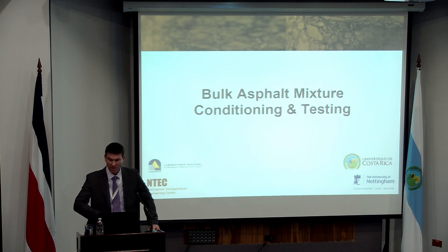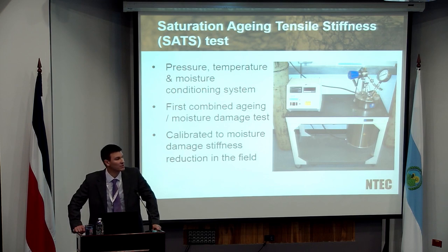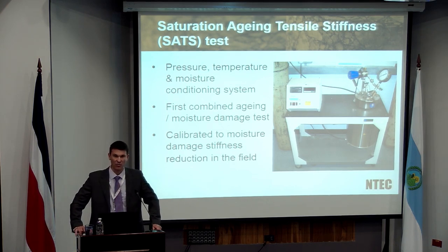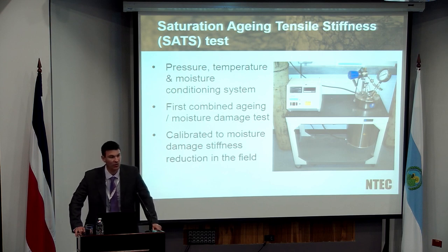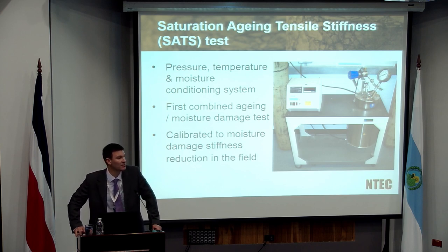So what about the asphalt mixture itself? In this particular case, we have used a test that was developed in Nottingham, which is a combined aging moisture damage test. So it's a test that is effectively looking at two mechanisms in one. And we've done that because that's what happens in a road. Obviously, the road is experiencing oxidation throughout its lifetime in terms of the bitumen reacting with oxygen, becoming harder, more brittle potentially. But once you've introduced water into the equation, you're obviously also having an effect of moisture damage and potentially stripping or debonding. And this test effectively allows you to take your asphalt specimens and do both types of distress simultaneously.